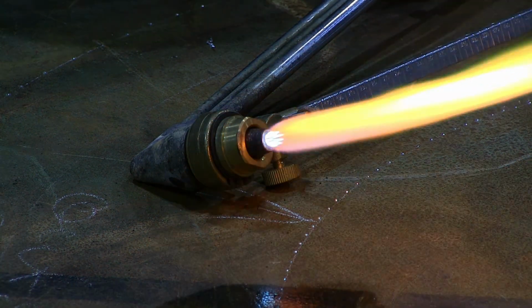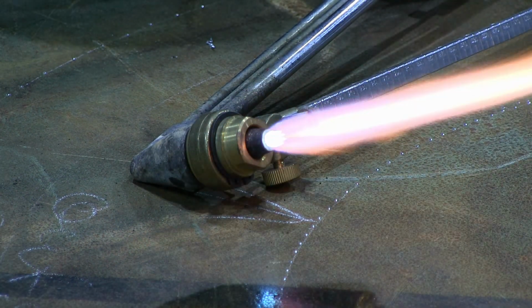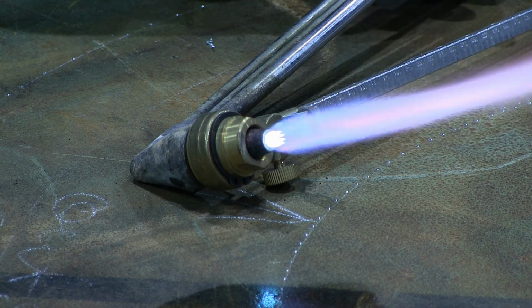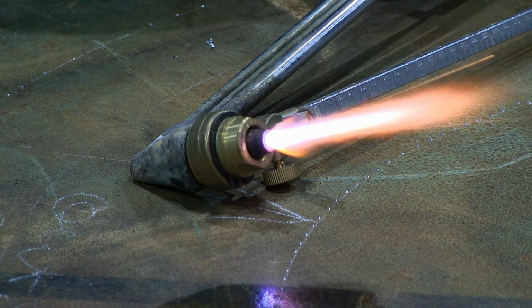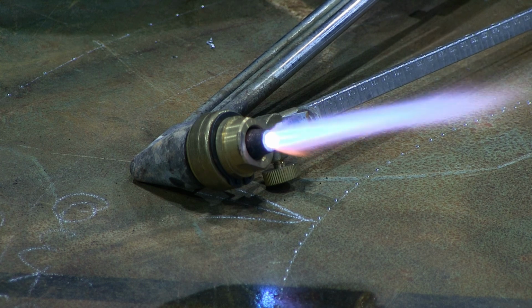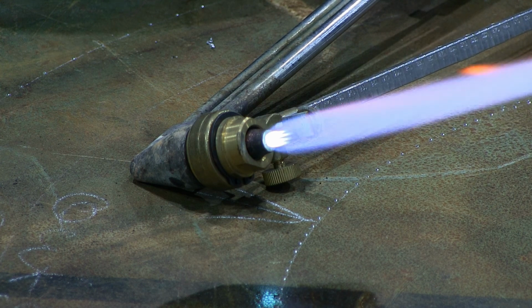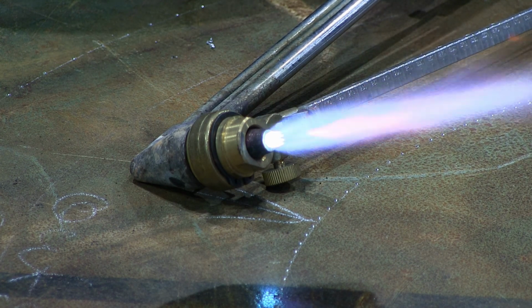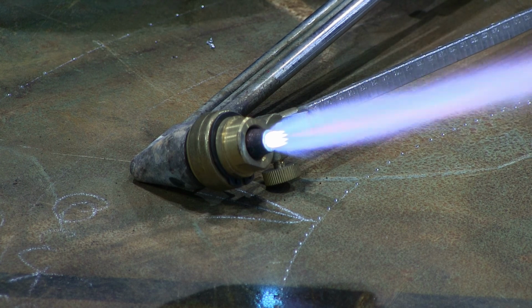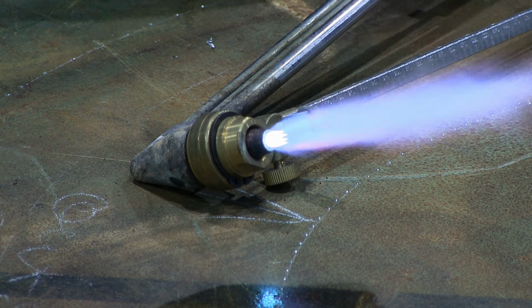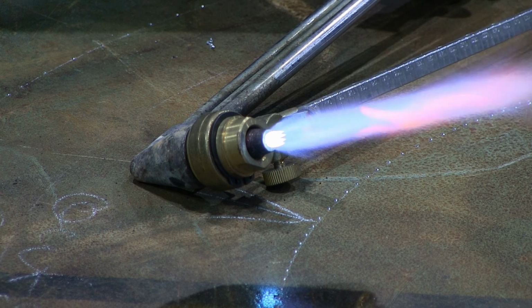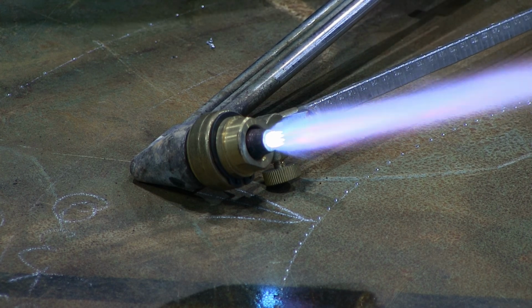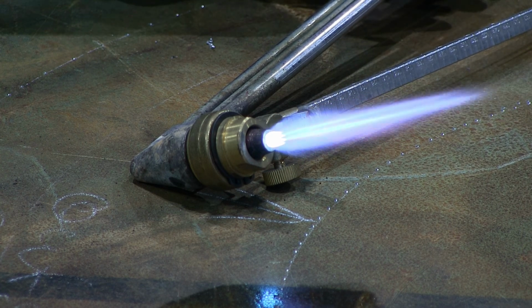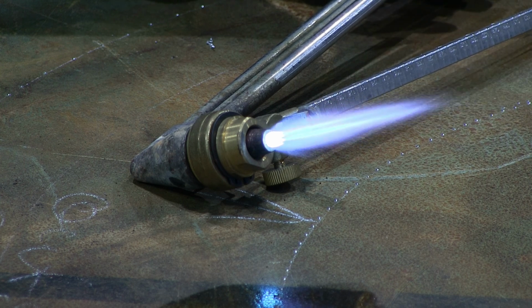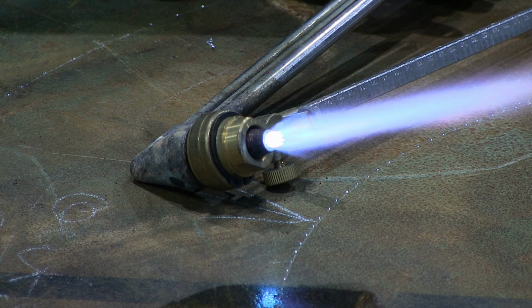With the flame, you just add enough heat to cut the thickness of material that you need to. That comes with experience, but there are ways and means to judge it, and you adjust the mixture such that you burn all the fuel gas with your oxygen, and when you hit the cutting oxygen, there should be a nice jet. As you can see, if this jet is nice and even and straight, quite prolonged, that means you have cutting oxygen which will cut nice and evenly.